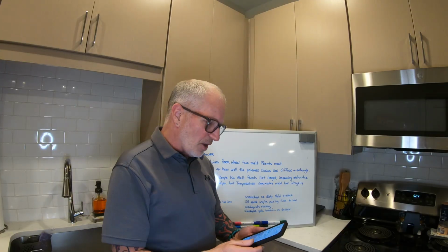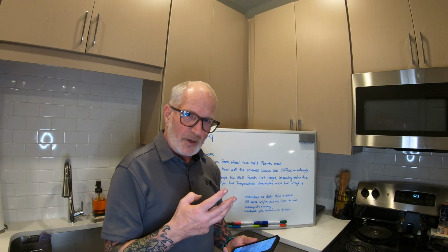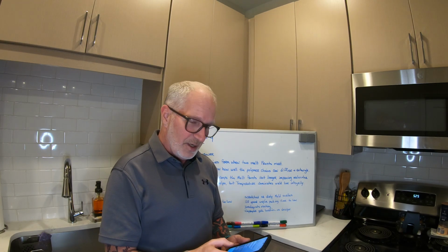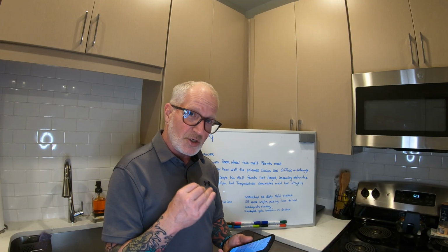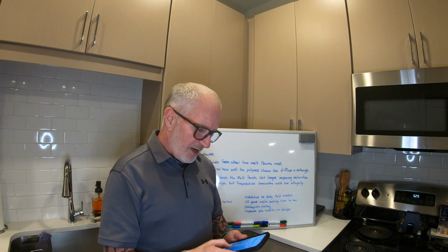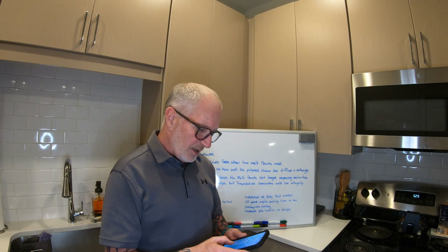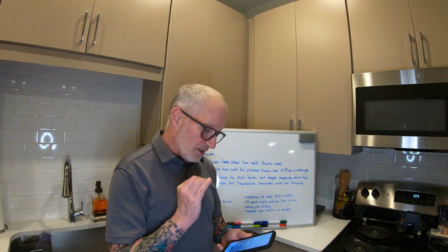I couldn't get on the board, but I was going to go over a little bit more with you guys as well. So I do have the 3 M's. So the 3 M's are always machine, material, and mold. That's how I always do it. These are possible scenarios of what you can do to try to fix it. So on the machine side, you can increase injection rate, adjust profile faster, increase injection pressure, increase pack and hold pressure, increase pack and hold time, increase barrel temperature, increase shot size, increase screw back pressure, increase nozzle orifice size. Those are all on the machine side.